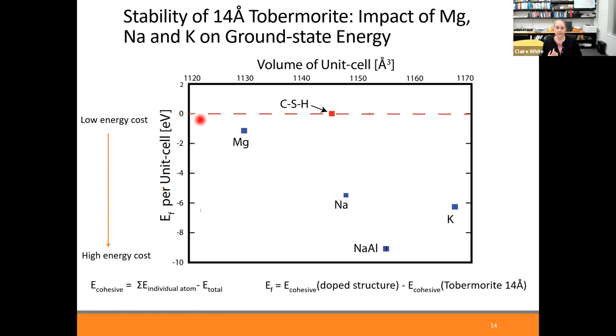And specifically, if you do the substitution, do you have a decrease in this formation energy? If so, that means that there's an energy penalty to having that different atom in your structure. And overall, that means that your structure is less stable. It could be more prone to change over time. And so what you see on this slide here is if you replace a calcium for a magnesium in the interlayer, it is less stable. If you replace the same calcium with sodium, it's even less stable compared to the magnesium. Likewise, if you do a sodium substitution and also an aluminium for a silicon site, it ends up down here. And then potassium's over here as well. I'm not going to go into the volume for the time being.